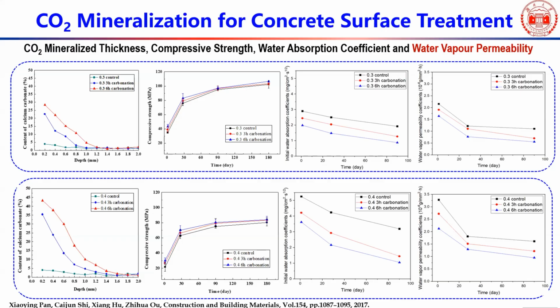Then if you look at the calcium carbonate content changes from the surface, the top one is for a water-to-cement ratio of 0.3, and the bottom one is for a water-to-cement ratio of 0.4. The initial surface content is almost 45%, but at a depth of only about 1.6 millimeter it becomes basically uncarbonated. So here, what I want to point out here.